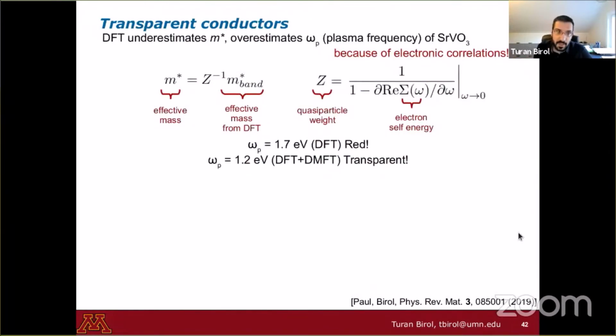Now, the reason that this happens is that the effective mass, which is related to the inverse second curvature of the band energies in DFT, which I denote as M band, is different from what you get in DMFT by a factor of Z. This Z is the quasi-particle weight or quasi-particle residue, and you can expand it to first order in terms of the electronic self-energy, which is by definition zero in DFT. So we find a Z of 0.55, so we find narrower bands. So electrons behave just like twice as heavy in DMFT compared to DFT.